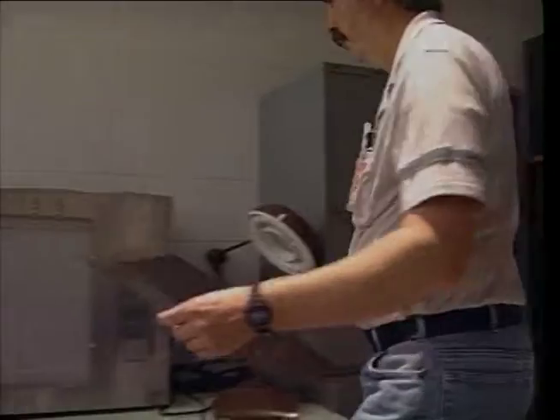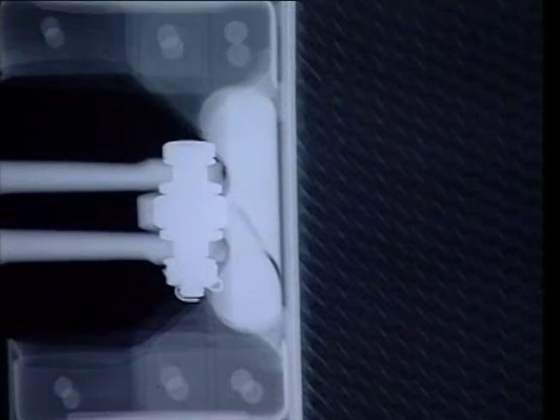After processing, the dried negative image is retrieved and examined over a light box for the telltale changes in density that would indicate the presence of corrosion. Accurate analysis requires skill and experience. In this negative image of an elevator trim tab, the treacherous-looking anomaly is not a crack, only a bead line of epoxy. A well-exposed radiograph in the hands of an experienced technician can be a highly reliable inspection tool.